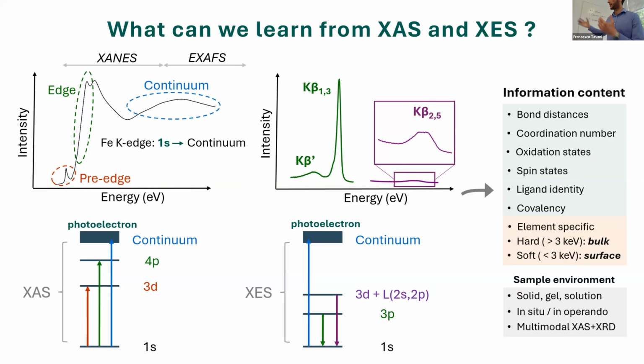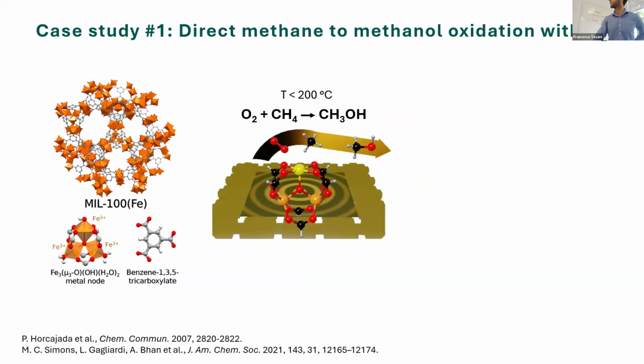So we can investigate solid samples, such as MOFs and reticular materials, gel samples, solution samples as well. And we can do this in real time, so through in situ experiments as the given process we are interested in is occurring. We can also perform multimodal experiments, by combining a technique which is sensitive to local environments, such as XAS, with, for example, conventional X-ray diffraction, which tracks the global structure modification.